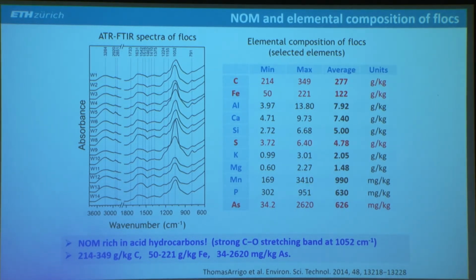The elemental composition showed that there was a lot of carbon. So here's the summary. There was between 21 and 35% carbon, so very rich in organic matter. We had 50 to 221 grams per kilogram iron, so fairly rich in iron. I will show what this iron is in a minute. And we had up to 2,600 ppm or milligrams per kilogram of arsenic in these flocks, so they're very rich in arsenic.